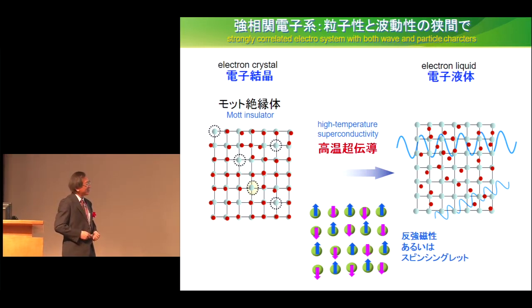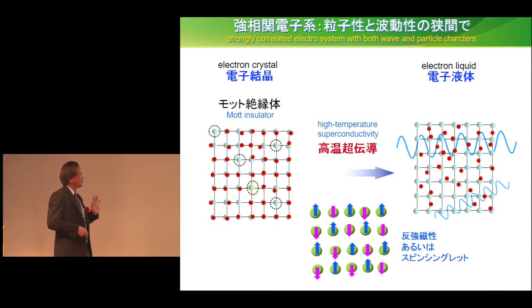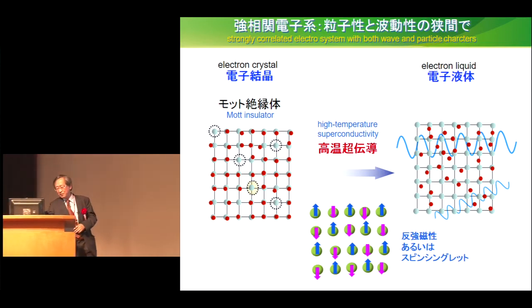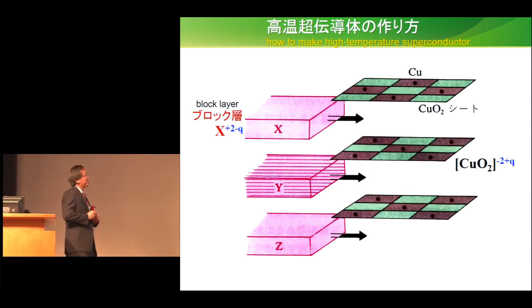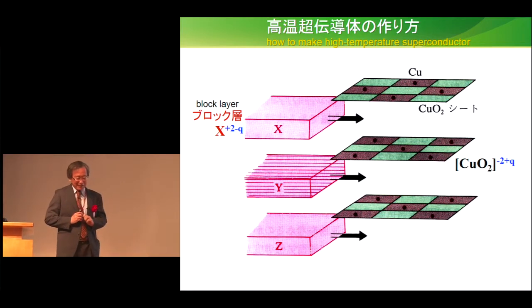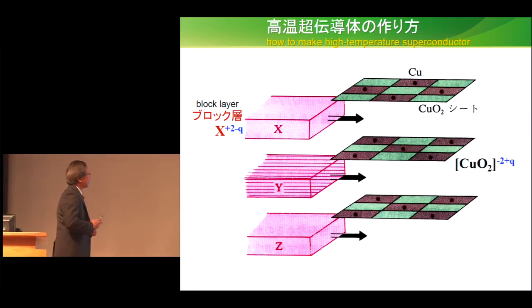The high temperature superconductivity takes place when a small change takes place from the state of Mott insulator to electron liquid under a very cold temperature. So it's just near the state of insulator that high temperature superconductivity may take place. So this is not a state which is totally different from the Mott insulator. Then how can we make a high temperature superconductor? We produced a recipe how to make it about three decades ago.